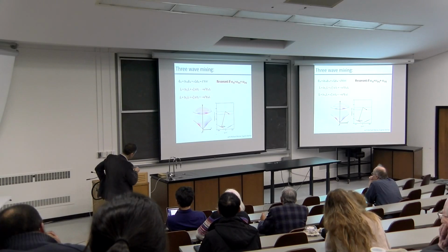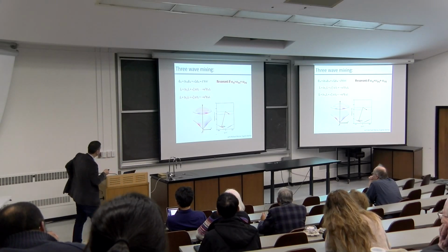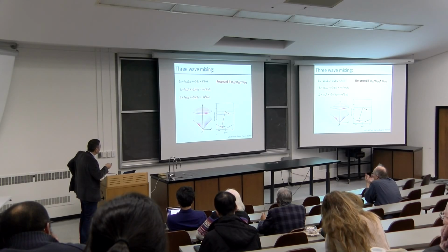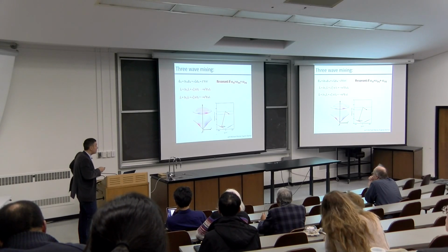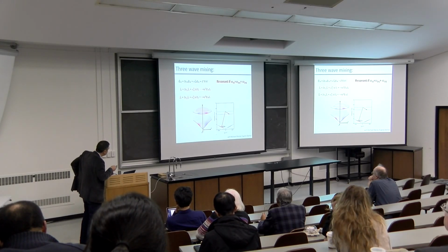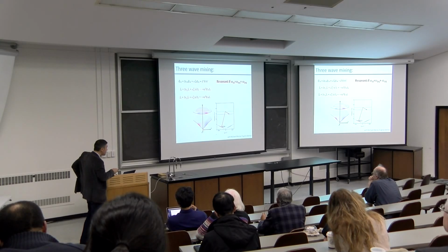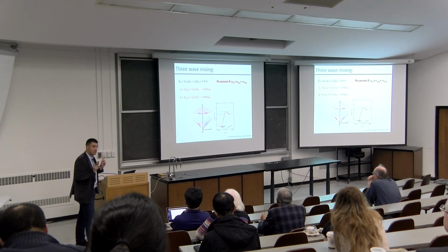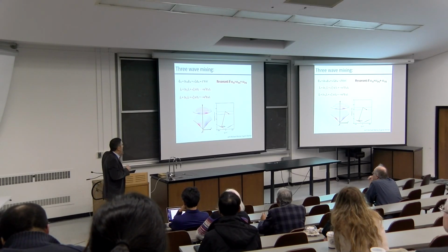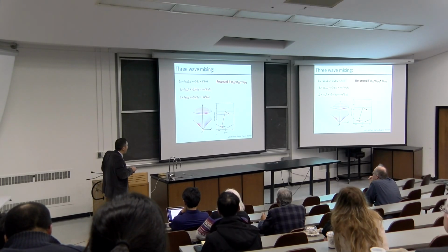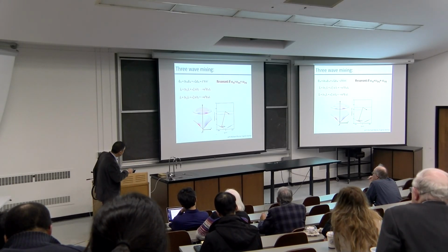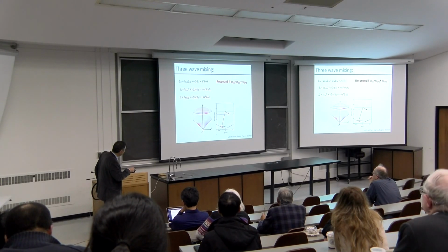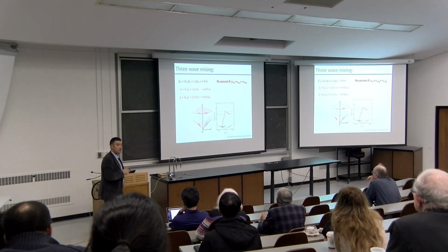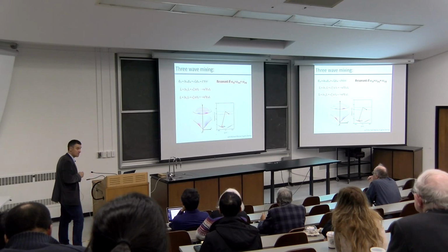So what this three-wave mixing process tells you is that pumping this phonon parametrically drives oscillations in these plasma modes at finite momentum. The important thing is that because of symmetry, this does not happen at k = 0, but it only happens at finite momentum. Basically, the way one has to think about this is that this phonon generates pairs of these Josephson plasmons, and it selects a pair of momenta, plus k and minus k, so that the frequency is respected. Okay?